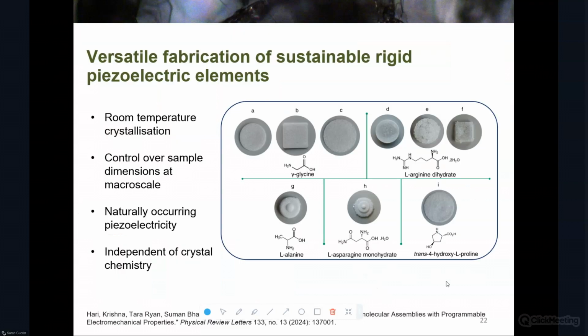It completely covers that bottom electrode. That means that we can place a top electrode on top of it without shorting and then turn it into a device for energy harvesting applications. So this was with L-alanine, but Krishna has gone on to do this for a number of different chemistries, and also, as you'll see, develop them without a substrate at all, which is also cool. So we went from using those conductive substrates, which allowed us to optimize the conditions for crystallization for this material. And then we wanted to get rid of the substrate altogether.